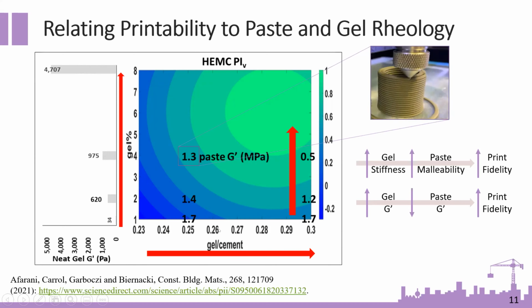Furthermore, as we increase the gel to cement ratio, we see that the cement paste storage modulus decreased and the printability improved. So we can say that as we increase the gel concentration, gel stiffness increased, the paste malleability increased, and the print fidelity increased, which you can clearly see: as the gel concentration increased, gel storage modulus increased, the paste storage modulus decreased, and the printability improved.